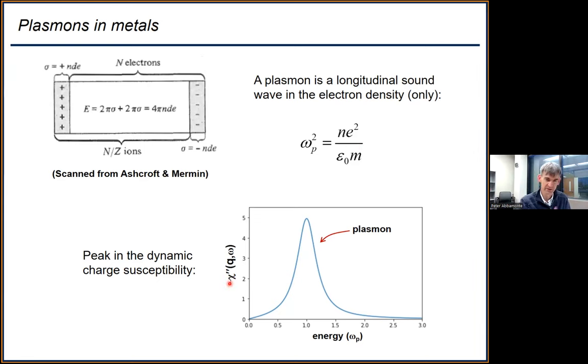There's another quantity that I'm going to discuss in a few minutes called the dynamic charge susceptibility, which is related to the dielectric function. And the experimental signature of a plasmon is clearest in this susceptibility, which I'm going to call chi. So if you measure the imaginary part of this thing at some fixed momentum as a function of energy, then what you'll see is a peak at the plasma frequency with a width that's given by the lifetime. So this is the most direct way to show that a plasmon is present in a metal. The reason I bring this up is because you can measure this quantity by scattering electrons off a metal, which is how plasmons were originally discovered and is also how we found the demon. But I'm getting ahead of myself.